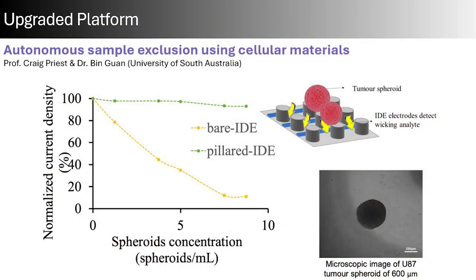So this is just some of the work that we've done where they've looked at the bare IDE. So this is without the pillars. And you can see that the normalized current density, so that's just meaning what current goes to the electrode, decreases. So it goes down to 20%. And we postulate it's because the larger tumour spheroids that we have put in solution are blocking anything from happening. When you compare that to the pillared IDEs, we get quite a constant 100% transfer of the electrons. So it means that it's definitely anti-fouling is what we've sort of succumbed to.